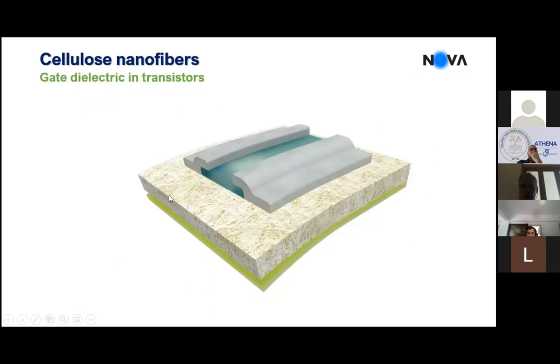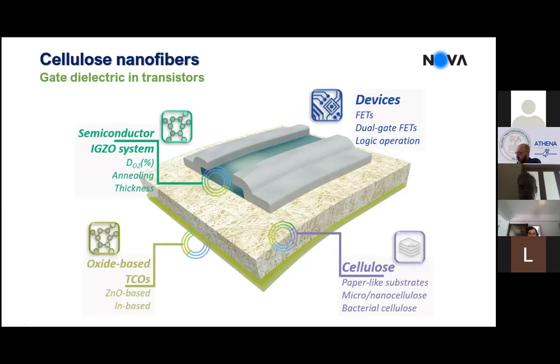And so the strategy to make paper work as a dielectric is this one that I presented before. So you have the paper as a substrate, but also as a dielectric layer. Now if it works as an electrolyte, the thickness will not be relevant, as I explained before, as long as you are in the capacitive regime of these electrolytic membranes. You have the semiconductor on one face, the source and drain, and you have the gate electrode on the other face. Okay, so if you tune the properties of the paper to be a good electrolytic membrane, you can use this type of structure.